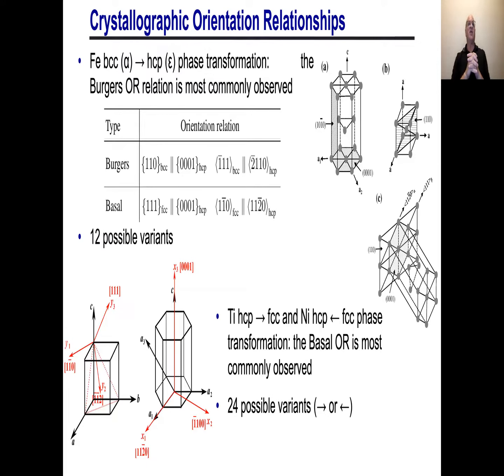Now, the other case I'm going to look at later on is titanium and nickel. Titanium undergoes an HCP to FCC transition with the application of pressure, and nickel undergoes an FCC to HCP transition as a function of pressure. Here the orientation relationship is the basal orientation relation, and that's shown here. Close-packed here, close-packed there: 111 in FCC, basal in HCP, and again the same sort of close-packed direction in the FCC and the 112-bar-0 in the HCP. Okay, and that's shown here.